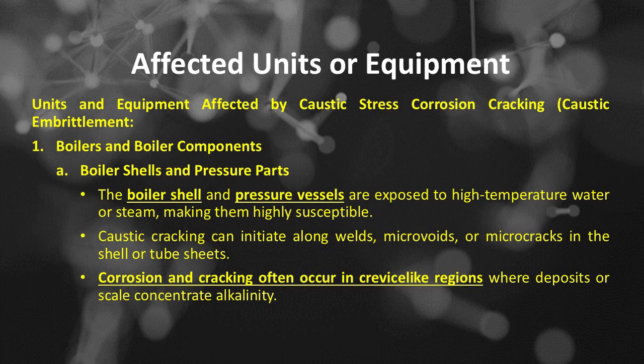Number 1 is boilers and boiler components, which includes, number A, boiler shells and pressure parts. The boiler shell and pressure vessels are exposed to high-temperature water or steam, making them highly susceptible. Caustic cracking can initiate along welds, microvoids, or microcracks in the shell or tube sheets. Corrosion and cracking often occur in crevice-like regions where deposits or scale concentrate alkalinity.